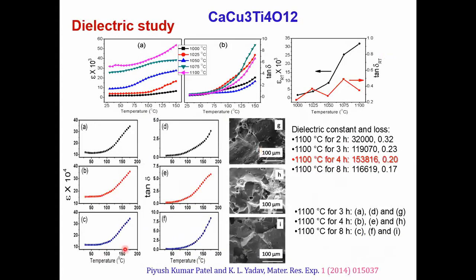If you see, these materials are almost constant up to 80 or 90 degrees centigrade. But the industry standard samples shown, NPO, had a constant value from -50 to 125 degrees centigrade. Here we have not tested below room temperature; from room temperature to 200 we have done, but up to 100 you can take it as a constant value.